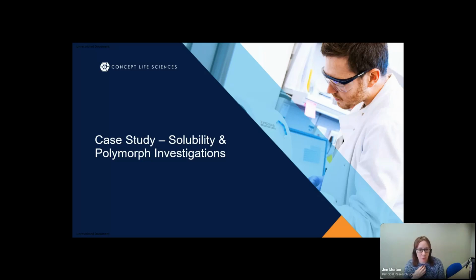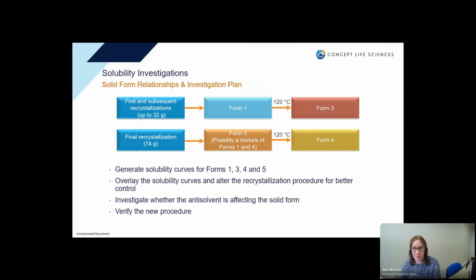Lovely. Okay, so now we will carry on with the case study work that we did using the Crystal 16. Just before we do that, I'm going to recap the relationships between the different solid forms as a starting point. So our first recrystallization and most of our recrystallizations through the process work up to 32 grams gave us form 1. And form 1, when it was heated to 120 degrees, converted to form 3.